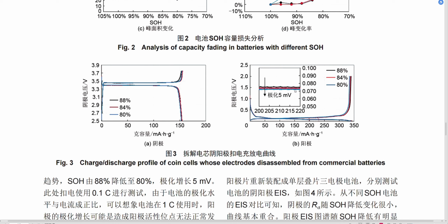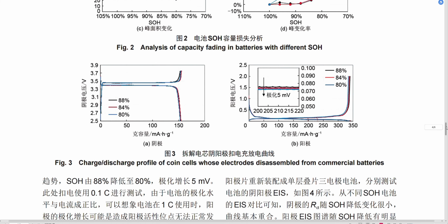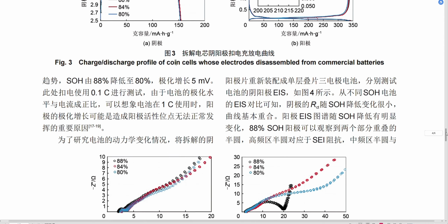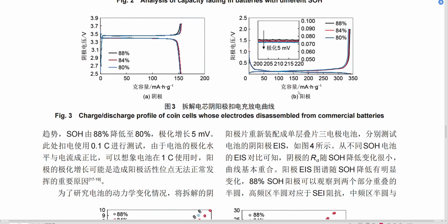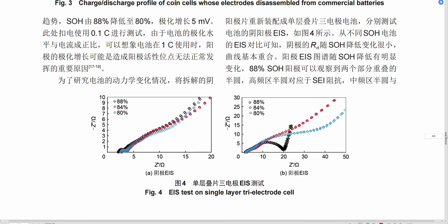They are basically trying to point out the overpotential increasing about 5 millivolt near the end of the charge discharge region. Their claim is that this 5 millivolt is somehow the major contribution for the kinetic or rate performance decrease from the anode side. What they have done later is present other data to give more evidence to this discussion.